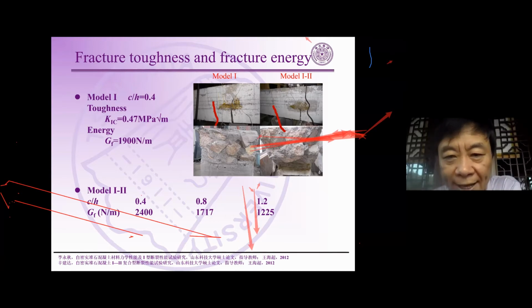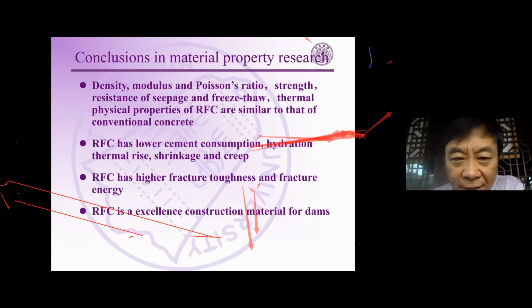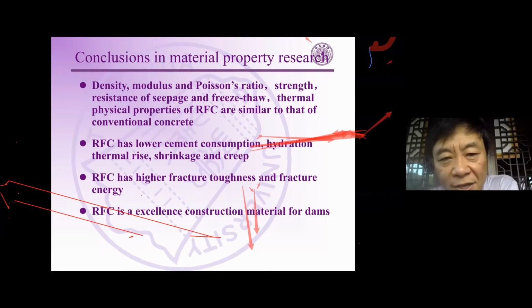We can also conclude that the fracture resistance of the rock-fill concrete is much higher than the conventional concrete due to the large rocks. The large rocks can prevent crack propagation. So maybe the initiation of cracking in the concrete is similar, but the micro cracking in the rock-fill concrete cannot propagate easily due to the limitation of the large rocks. And then we can conclude that the density, the strength, the resistance to seepage and freeze-thaw, and the thermal physical properties are very similar to those of the conventional concrete.